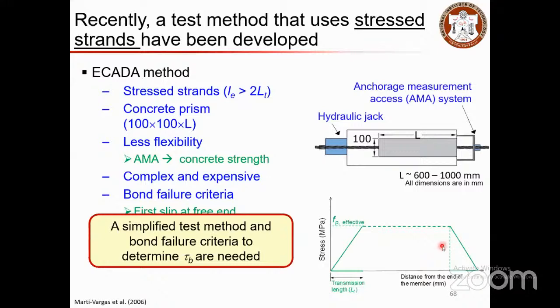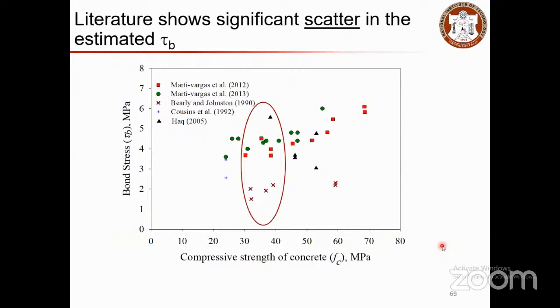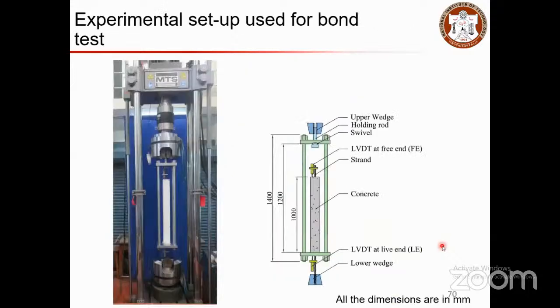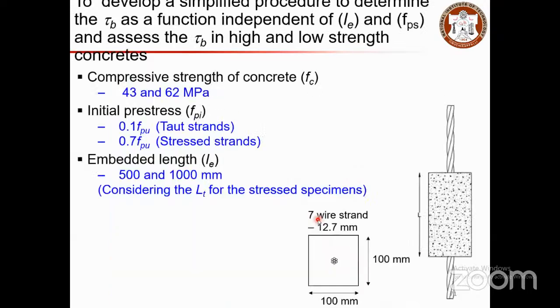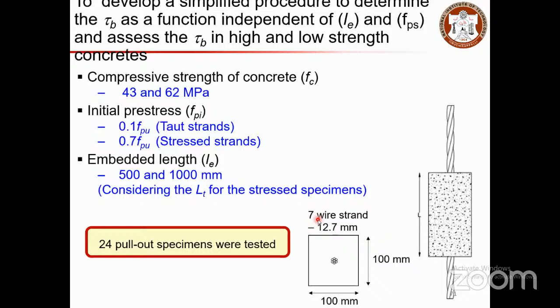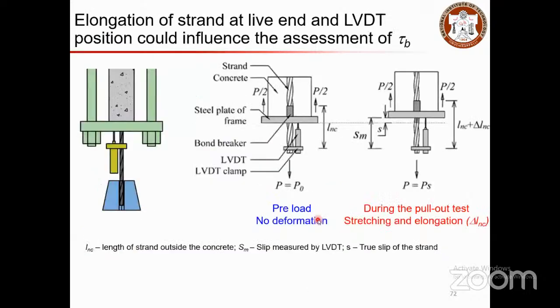So we decided to come up with a simple test method for determining the bond criteria. Based on that, the simple test method is proposed, and a 1 meter long prism specimen is cast with stressed strand. The stress level is 0.7 fpu, and the whole setup is placed in an MTS machine to do the pull-out test. This end is fixed, and when it is moved, the strands are pulled out from this end, and two measuring devices are placed at the ends to measure the slip at the ends of the member. Two different pre-stress levels and two different embedded lengths were considered.